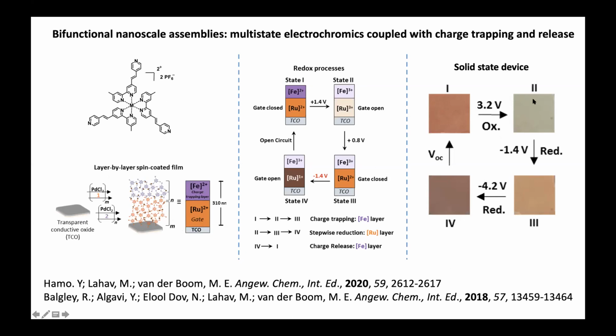And now we can selectively reduce only the ruthenium, and the iron stays in this higher oxidation state. The charge is essentially trapped in the iron layer. Then you can reduce the ruthenium complexes further to ruthenium 1. You open a channel for electron transport, and you can reduce the iron back to its ground state. So by combining those materials, those films, cleverly, you can generate multi-state electrochromic systems.